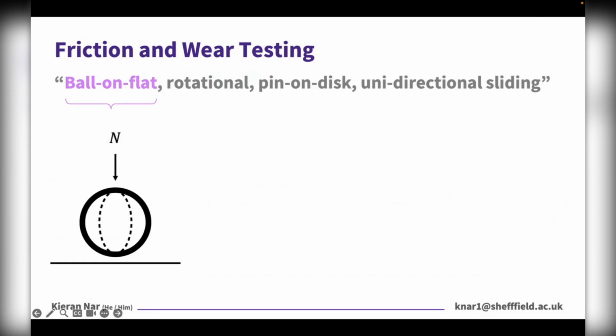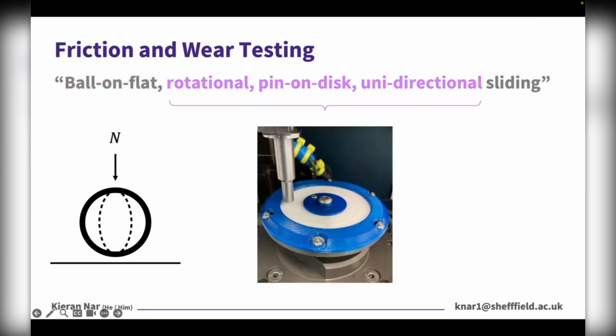we chose to utilize a ball on flat configuration so that we get point contacts, primarily to avoid any misalignment issues, which are more typical with flat on flat contacts. And the rest of that term just describes the way the test was set up, as shown in this photo. But if you aren't too familiar with tribology test methods, this one is akin to a record player, where I guess our polymer laser sintered disc samples were our vinyls, and they rotated relative to the pin or the needle in the context of a record player.